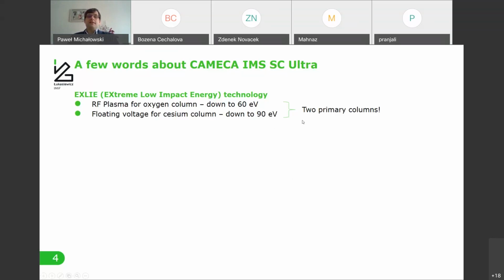The other thing is that these two primary columns are completely separate, so they're optimized separately with different angles, and that also gives the opportunity to tune the incident angle of the primary ion, especially for the cesium column, by applying this floating voltage. We can indirectly change the incident angle. As you will see, in many cases, I'm using a high incident angle, well above 60 degrees from the normal to the surface, which gives some new opportunities to perform analysis.